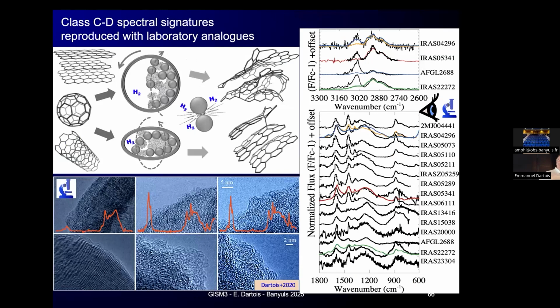You can use other techniques. These are mechanochemical techniques used to produce also some polyaromatic systems by putting basically a lot of energy, locally not at equilibrium, onto initially very graphitic or nanotube or fullerene systems. And in the presence of hydrogen, you create a lot of defects in the system, and you can reproduce the observation of these class C and D structures. And here you have the transmission electron microscope images of the deformed structure you get. So some people look at this and say it looks like a fake soot, but again, it's something that we can produce in the lab, not necessarily with the same kind of size as you have in space, but internally the structures are close enough to what you observe in infrared.